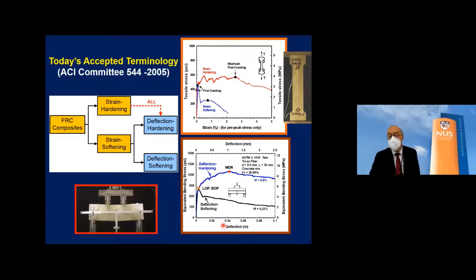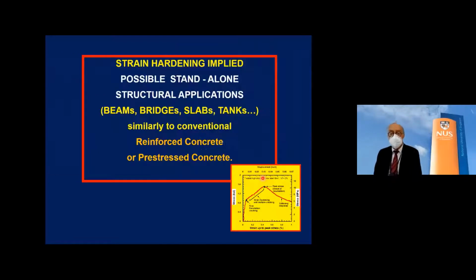And you would agree with me, let's look at deflection, because this is a common application, a small beam, a small slab. You would agree with me that if you have a response like this of a given construction material, you could use it for some structural application, because you could use your service condition here. You have maybe a factor of 2 for the ultimate. Ultimate is not brittle. You have a descending branch that gives you warning. So it is a structural material that I can use, but it has to be deflection hardening, not softening, or strain hardening or softening. Okay.